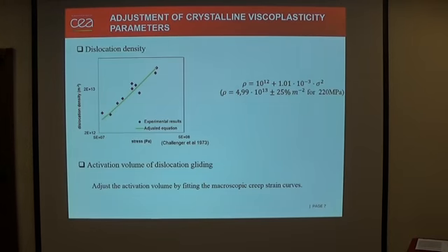For the dislocation density, we use the experimental results of the literature, and we propose this equation, an adjusted equation to calculate the dislocation density as a function of the applied stress. And we will fit the activation volume using the macroscopic creep strain curve.